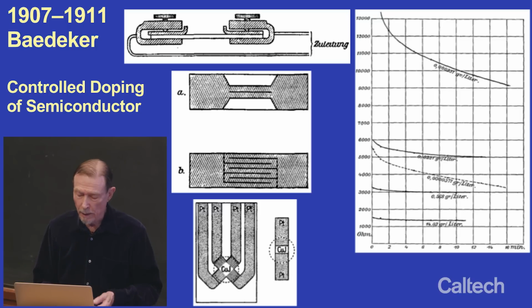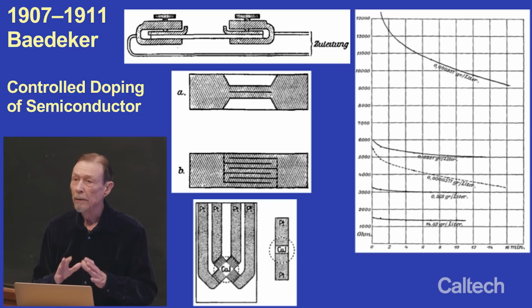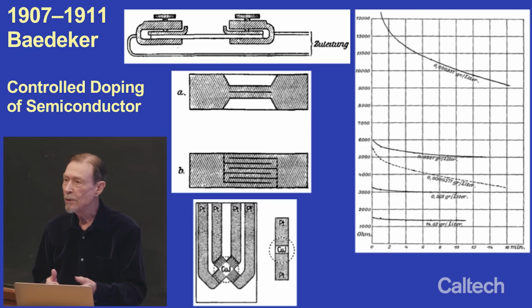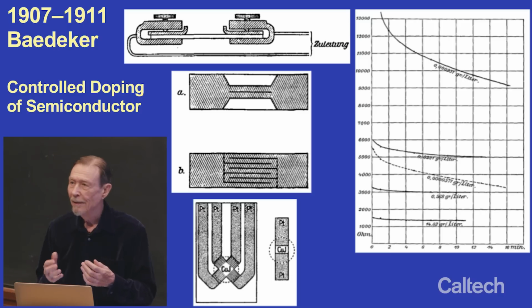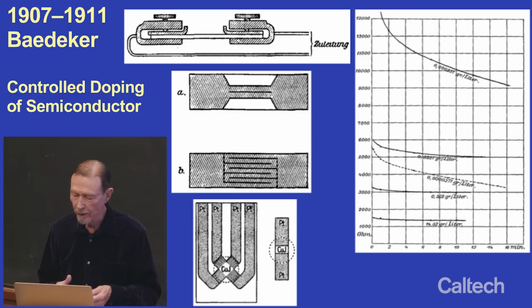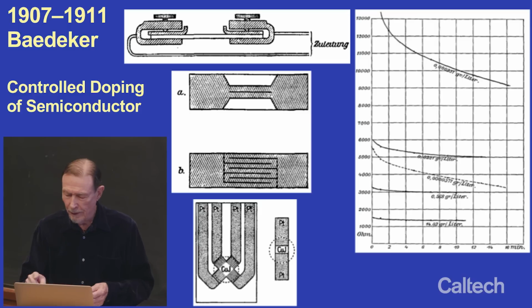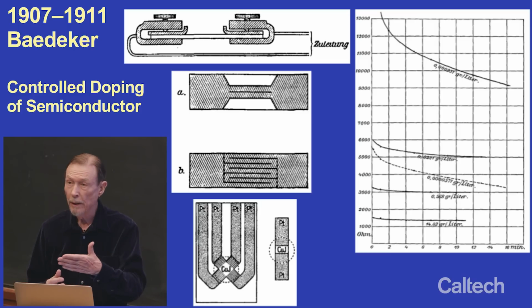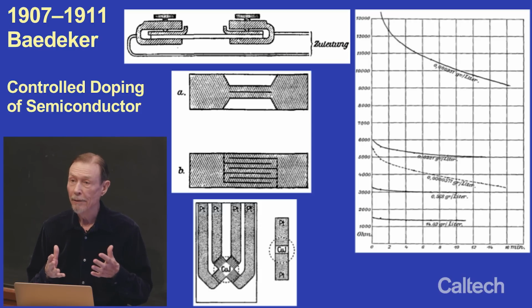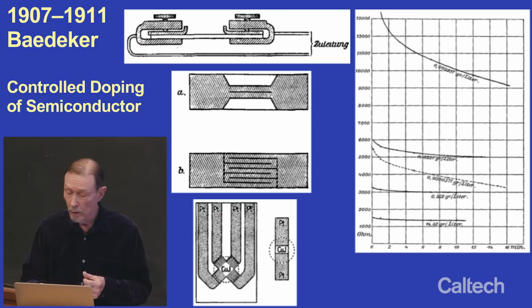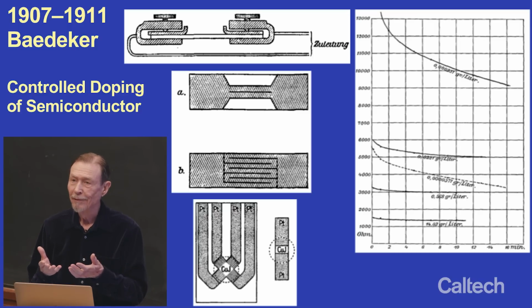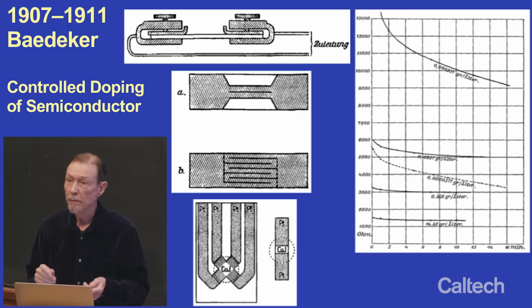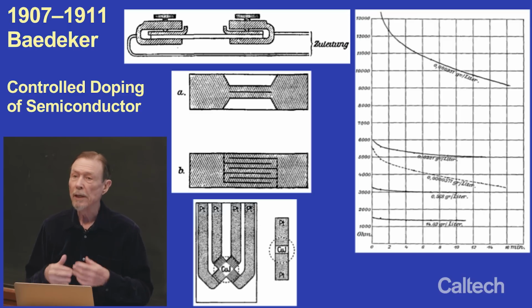And then he treated the copper film with iodine, either in a vapor or in a solution, until it was copper iodide. Beautiful, clear semiconductor film. It was a precursor to the conductors we now have on glass in all of our displays, the conductive, transparent conductors. He was the originator of all those. And he found the plot that you showed there, that as you put more iodine in the iodide film, it conducted better. So if you had a low density of iodine in the solution you treated this film with, you got a high resistance. It didn't conduct very well.